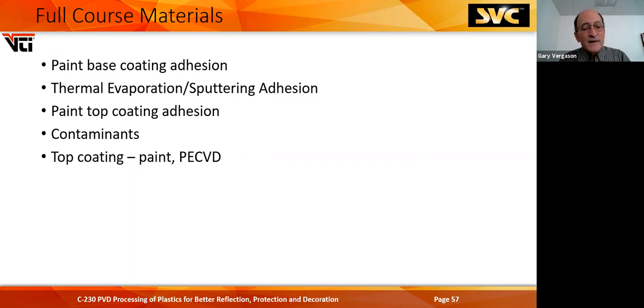Okay, these are other areas that we're going to get into. Paint-based coating adhesion. So you got the adhesion of the base coat to the substrate. You got adhesion issues from the metal layer to the base coat, or the metal layer to the substrate. Top coat to the metal layer. You can have contaminants in there, and you can have issues with your HMDSO top coat as well as the paint.